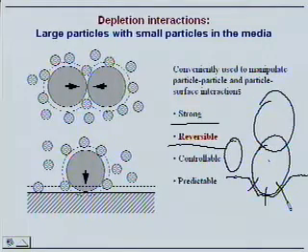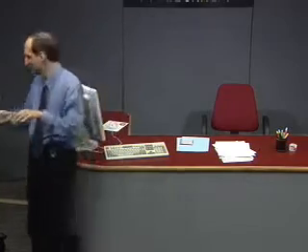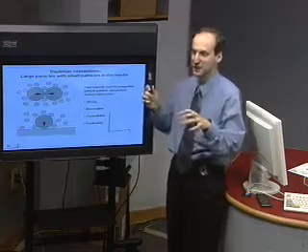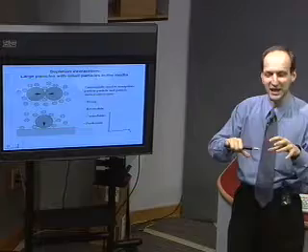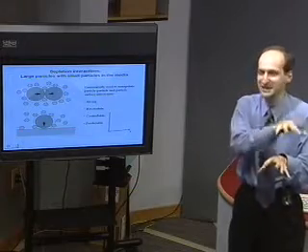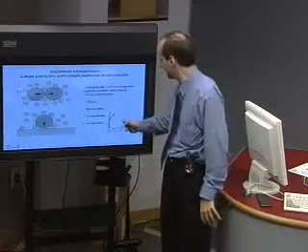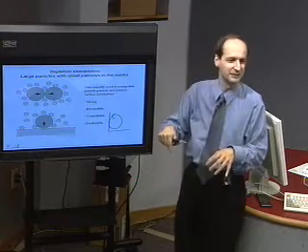So the equivalent is now you make some microfabricated surface. You put pits on the surface, or you put edges. You can just put an angle actually. Then you put large particles. Then you put small particles. And the large particles all go and organize themselves where you would want them to be. If you have an angle like that, they're going to come here. If you have pits, they're going to go in the pits.